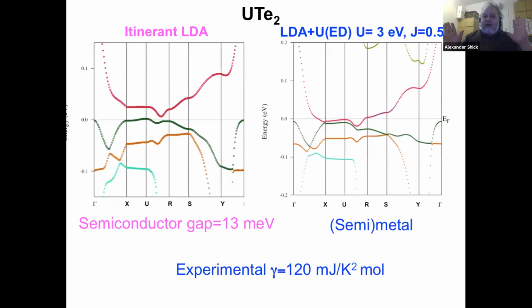Then the question is, how come it has a high gamma of 120 millijoules per Kelvin squared per mole? How can a semiconductor give such a high gamma? Moreover, how can it become superconducting? It means perfectly conducting. Therefore, one clearly needs to go beyond conventional density functional theory to deal with this issue. And since the material is not magnetically ordered, you cannot really straightforwardly use methods like LDA or DFT plus U, because they tend to work only for magnetically ordered phases, the purely Hartree-Fock-like calculations. So you have to go beyond Hartree-Fock. And that's what we did.